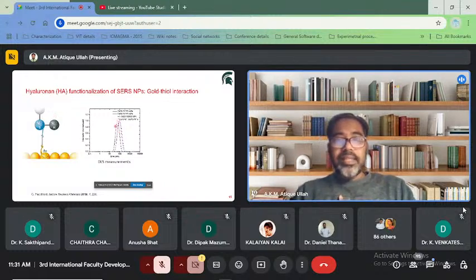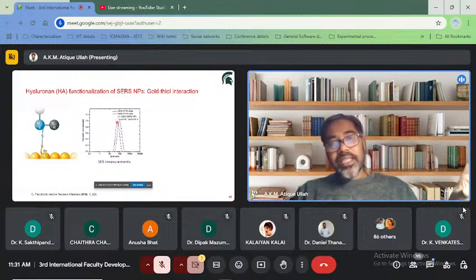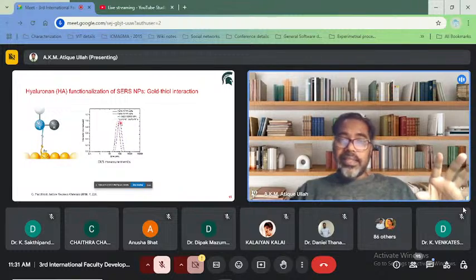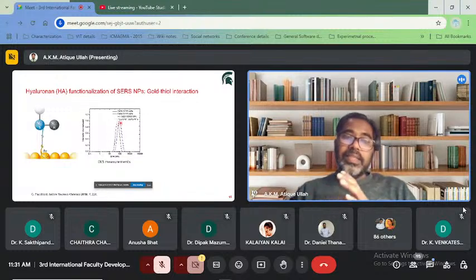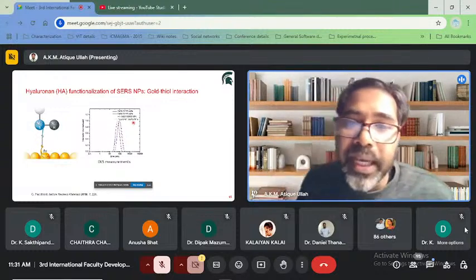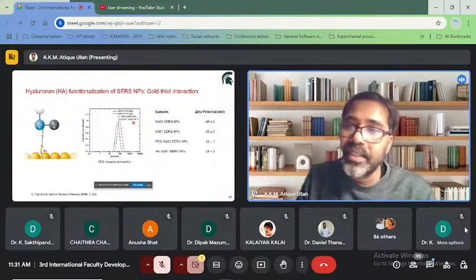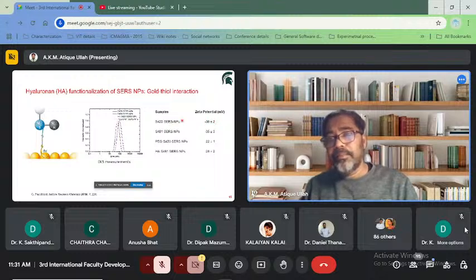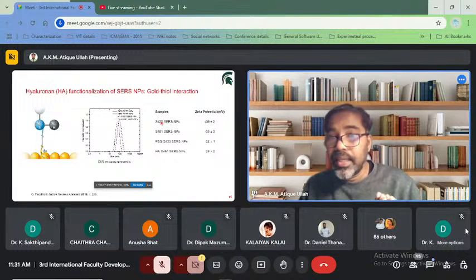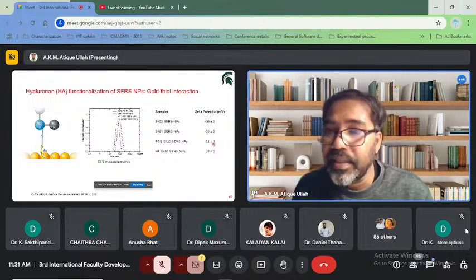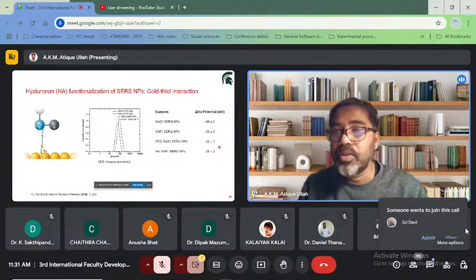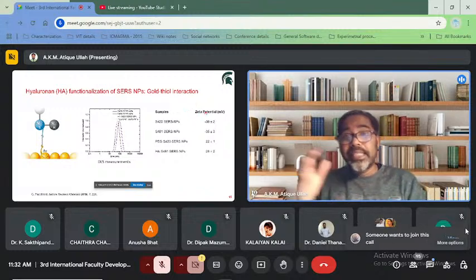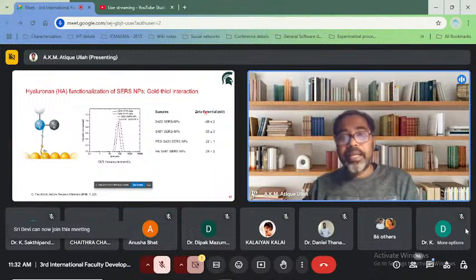You can see these are the DLS measurements without functionalization of the nanoparticles with HA and PEG, and this is after the functionalization. There is an increase in the DLS size. From this experiment, we can say that our nanoparticles are functionalized with the HA, that is hyaluronan, and the PEG. Also we measured the zeta potential. You can see this is the bare SERS nanoparticles, suppose S420, without any addition of PEG. With the PEG, there is a decrease of the zeta potential. In the case of the HA, you can also see a decrease in the zeta potential. So this increase in the DLS size and change in zeta potential is an indication that the SERS nanoparticles are functionalized with the PEG and the HA.